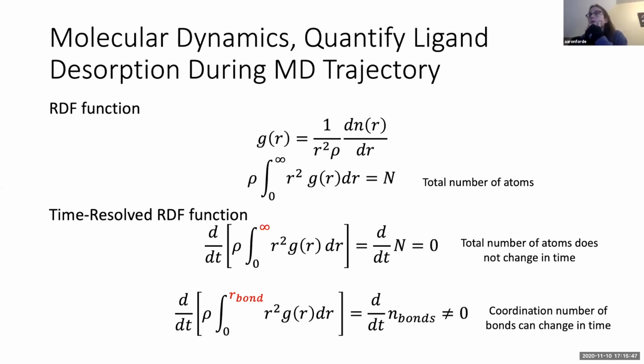Yes. And then you divide it by the surface of a sphere analytically. So to normalize, to avoid the quadratic growth with distance, right? Otherwise, if you do not do this normalization, 1 over r squared, and keep only dn over dr, it will grow quadratically because the sphere becomes bigger and the amount of neighbors on each next sphere is bigger.